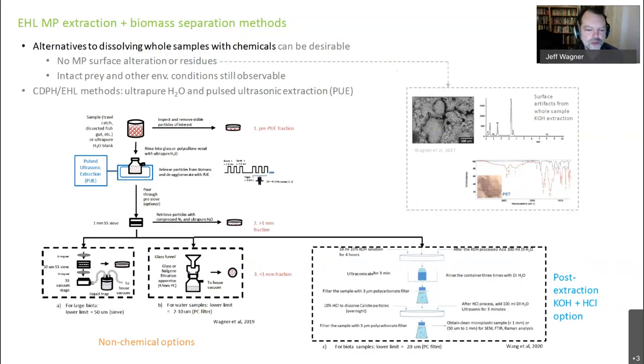So we tend to do a pretty thorough inspection under the optical microscope and various techniques of the sample, with as little distress to the sample as possible. And then after we've done that, we use a mechanical technique, pulsed ultrasonic extraction, to separate the biomass from the microplastics. For samples in which we wish to refrain from chemicals completely, we can then just deposit the samples on either a filter or collect in a petri dish, depending on the particle size and the amount of biomass. We also just published a paper where we did do chemical treatment of the final particles, and we feel that's a good compromise between getting very clean particles, but also being able to look at the sample pre-chemicals before you get to that point.